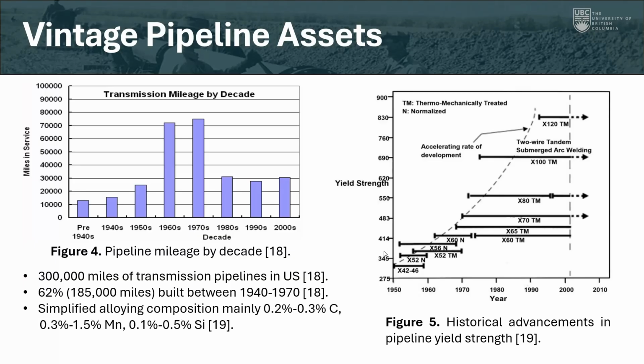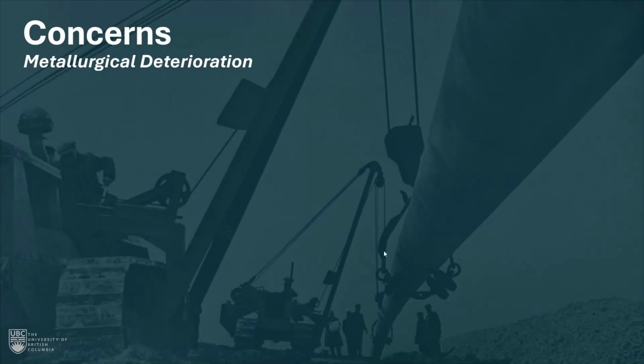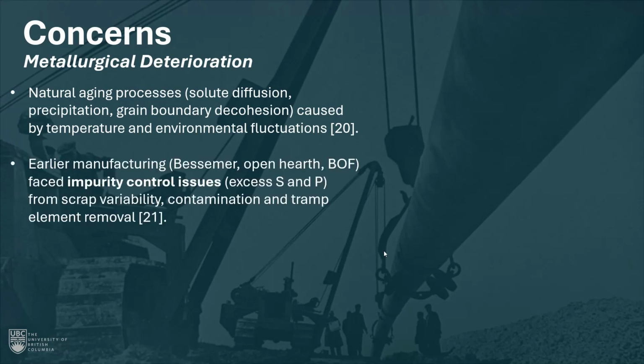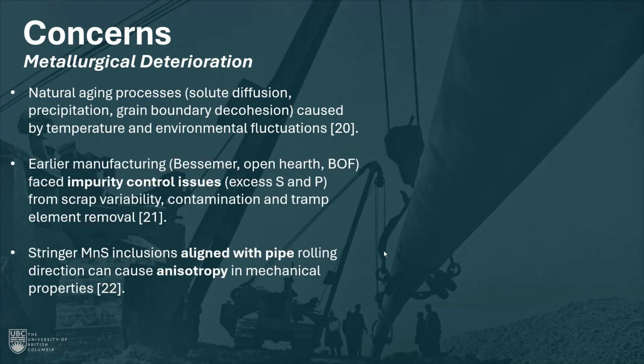While we looked at the thermodynamic constraints, we're also limited by the material constraints, specifically composition and manufacturing, where we see simplified chemical composition, so typically a higher carbon content, as well as low control over sulfur content. At that time, in the early 1950s, we wouldn't have seen as much control on desulfurization practices as we do see today. And so, just commenting on some of the metallurgical concerns we have.